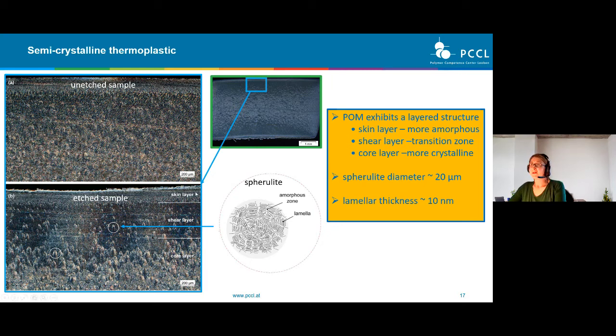which is a more amorphous zone. Then we have the shear layer, which is a transition zone, and the core layer, which is a more crystalline zone. And from these microscopic pictures, we estimated a spherulite diameter of about 20 micrometers. And these spherulites consist of lamella and amorphous zones in between, and the lamella thickness is only 10 nanometers.